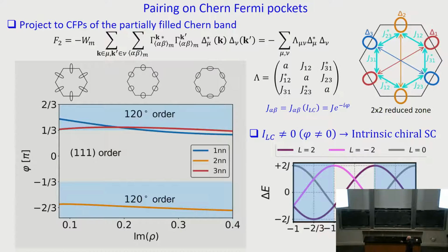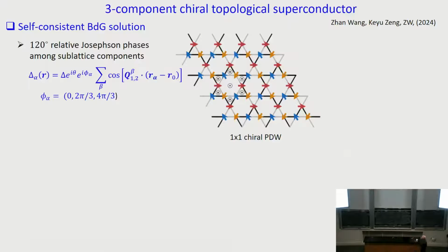And of course, the ground state turns out to be a 120-degree order. That is exactly this chiral state. I'm going to show you here. This is actually an illustration of a 3-component chiral state. Now, what's plotted here on sublattice 1 is the phase of one component pointing in one direction. Squint your eye, only look at the red arrow. That one sublattice is a component of the superconductor with a phase that I call 0, pointing to the right. And the blue sublattice component will be 120-degree rotated in phase. And the orange one is the phase of the superconductor order parameter rotated by another 120 degrees.